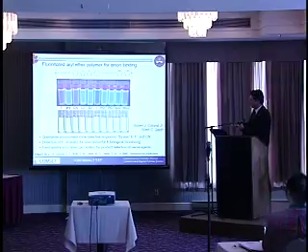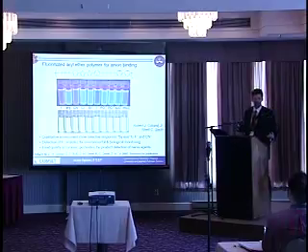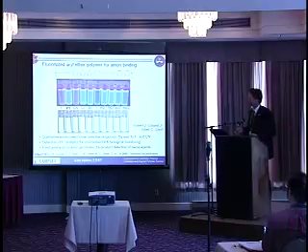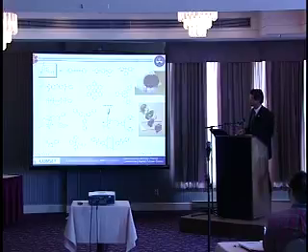But what happens is when it comes in contact with fluoride and cyanide, and you can see iodide to some extent, you get a turn-on fluorescence, which is nice. Most optical sensors, chem biosensors, are turn-off fluorescence, quenching fluorescence. But this is a turn-on, brilliantly turning on optical fluorescence. For fluoride, which is important for safe water, and it's also a hydrolysis byproduct of sarin and some other bad actors. Of course, cyanide as well.